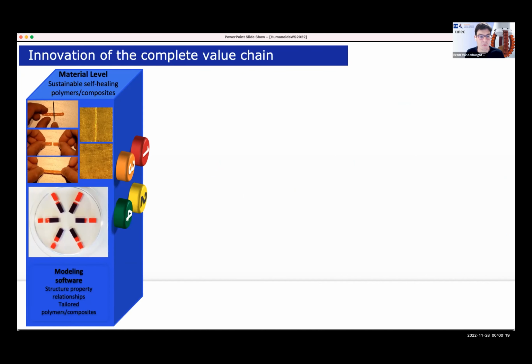So in our group, which has more than 20 persons only working on the self-healing, we have researchers working on the self-healing polymers. So we have a whole portfolio of materials, so we can make them very soft and very hard, very rigid, and we can also heal them together. And you see when you do a tensile test, it breaks in the weakest material and not at the interface, because usually when you make multi-material components, the interface of the material is the weakest component, which is here not the case anymore.